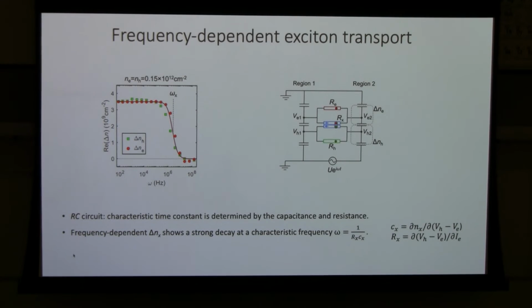We can make an analogy to charge behavior. The capacitance can be defined by Q over V. So we take the derivative of exciton density versus the voltage on the exciton, which is defined as the difference between the hole layer and the electron layer voltage. And then the resistance is V over I. So we define it as, again, the ratio between the exciton voltage divided by the exciton current. The capacitance can be simply calculated when we know the geometry of the system. And then by measuring this characteristic frequency, we can determine the effective resistance of the exciton.